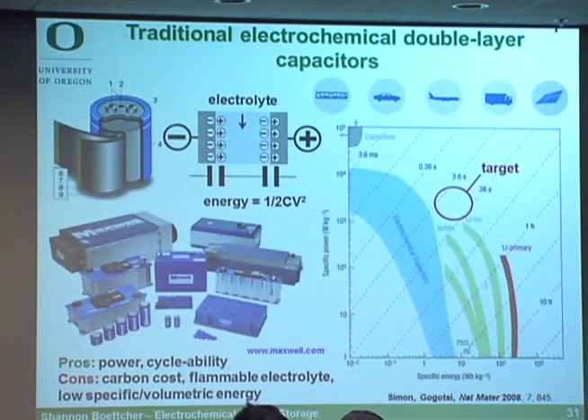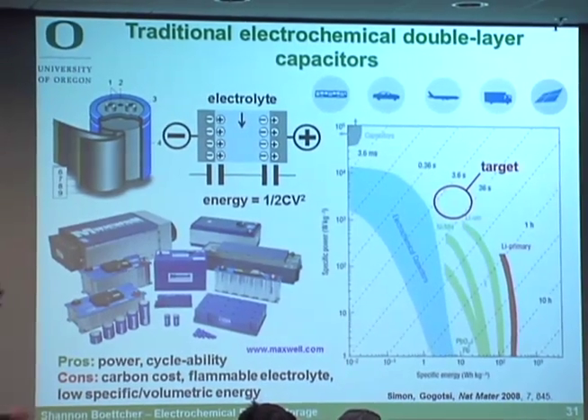The high power is because all the reactions are happening in electrolyte. There's no solid state intercalation, deintercalation reactions, so you can cycle them very fast and they last a long time. The challenge is that they're actually pretty expensive because the carbons need to be high purity and high porosity. You're using typically flammable organic electrolytes, and they don't store much energy. So what you'd really want to do is get something in this area here.